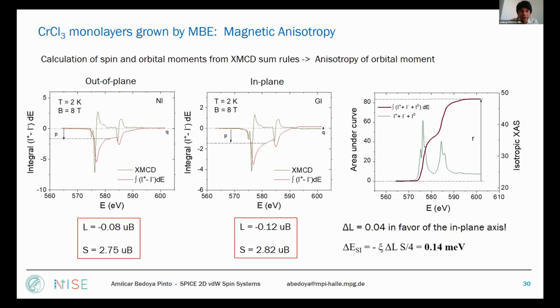So basically, we have here the XMCD measurements for normal and grazing incidence, and you know that you can use the XMCD sum rules to extract the spin and the orbital magnetic moment. To cut the long story short, we have observed a spin magnetic moment which is close to the 3 μB expected for chromium 3+, but we also have an appreciable orbital magnetic moment, and most importantly, we see a difference in magnetic moment when we put the field in plane and out of plane. That means that we have a small but measurable orbital anisotropy in favor of the in-plane easy axis.